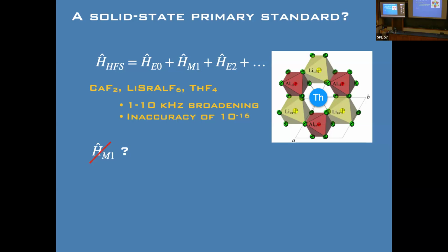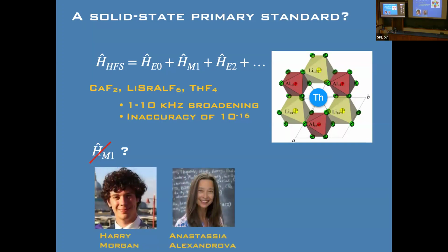All right. So to get rid of this broadening, we need to get rid of this magnetic dipole-dipole interaction. The problem is you need a really high band gap. And it's hard to get a high band gap without using a halogen, right? We need fluorine because it's very electronegative and all the halogens have nuclear spin. So, thanks to our work with Anastasia on some of this other chemistry stuff I do with molecules, I knew the right words to ask her how to solve this problem. So I want a molecule that replaces fluorine, and I don't want it to have any spin, but I want it to have a big electron affinity. And she had done a lot of work with superhalogens and realized that sulfate can be sort of a stand-in for fluorine. And if you remember your nuclear spins, sulfur and oxygen, you can get them with no nuclear spin.